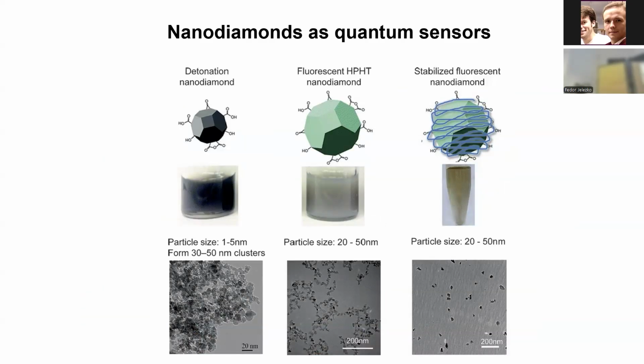Often the challenge of handling diamond particles is aggregation. When they come from reactors, they have a lot of sp2 groups, and they're hydrophobic and they tend to aggregate. So removing these unwanted sp2 groups and making them hydrophilic is an important field of research. Sometimes we try to stabilize them by wrapping charged polymers around them, and then because of electrostatic repulsion, they get stabilized in the solution. And this is important for any of this transport